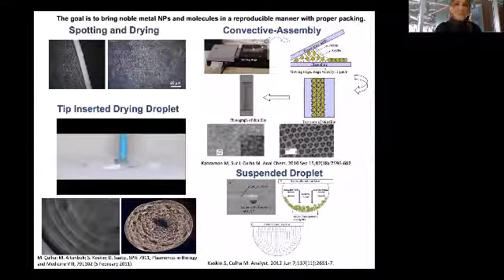And actually we contributed to the literature through this. When we realized that, we thought we had discovered something, but later we realized we did not really discover anything, because proteomics people all the time use this suspending and drying of droplets. But anyhow, we applied this approach in our research, and we showed that it is good. We also used convective assembly, and even dipped a hydrophobic tip into a drying droplet to control the distribution of molecular structures and nanoparticles in the drying droplet area. I think we showed the world that this is an important issue in this kind of research.